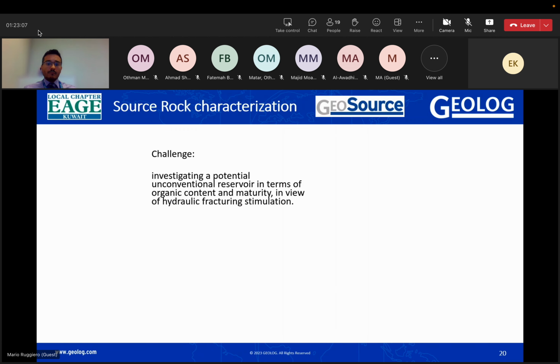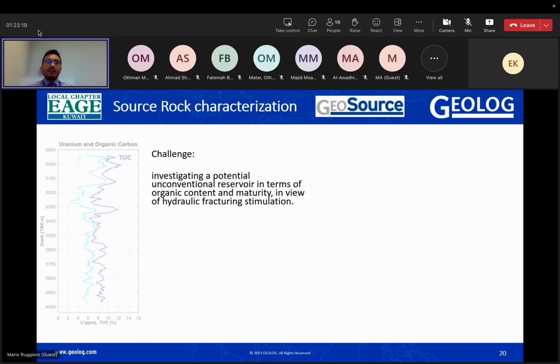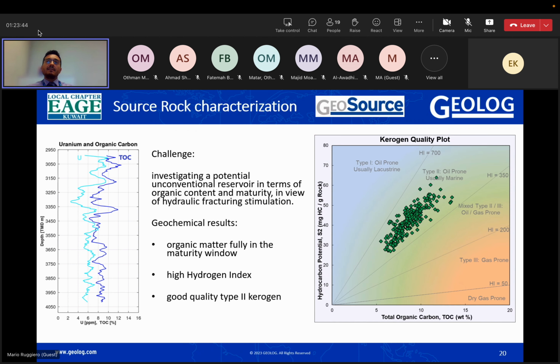Some examples: we want to investigate unconventional reservoirs to understand the organic content and maturity, in view of producing by hydraulic fracturing stimulation. So first, we see high TOC values all along the well, higher than 6%, with peaks around even 12%, so very high organic carbon content. And this is also directly proportional to uranium, which is an anoxic proxy by the XRF elemental analysis. And we also add the pyrogram data, in this case, the residual hydrocarbon potential, so the S2 peak.